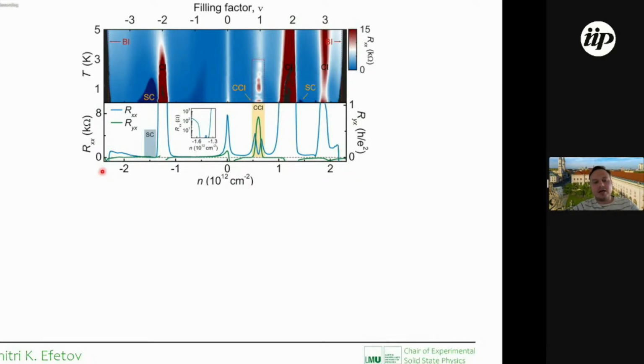And carrier density we can control in these systems very easily by applying electrostatic gates. So we can connect a small voltage to the device and capacitively induce electrons into the system. So without changing the device itself, without changing the chemistry of the device, we can just capacitively load electrons in and load electrons out. And we can basically translate this carrier density into electrons per lattice site, so basically electrons on a Moiré superlattice. And this is basically the axis on the top here. So filling factor 1, 2, 3 corresponds to 1, 2, 3 electrons per lattice site.